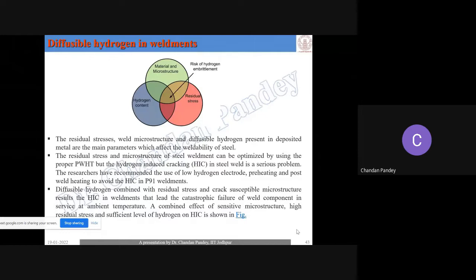Now, if you talk about hydrogen content, how will it create the problem? Actually, we get hydrogen content from two sources. One is the environment, and second, if you are going to use shielded metal arc welding or submerged arc welding to join a dissimilar plate, the covering that we use has moisture content, and if this moisture comes into the region of your weld metal, two types of hydrogen come. One is called trapped hydrogen, and one is called diffusible hydrogen. Trapped hydrogen, once trapped in the region of weld metal, will not create the problem. It remains at one position.